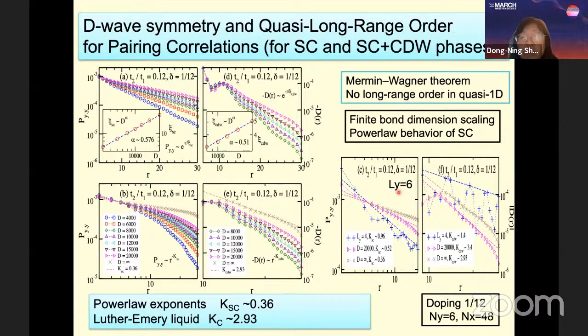We can also compare our system with different system widths. A system width of 6 has pairing correlation decaying much slower than the system with width 4. So the 6-leg ladder behaves more like a 2D system with much slower decaying pairing correlation, which indicates the superconductivity may remain robust in the 2D limit.